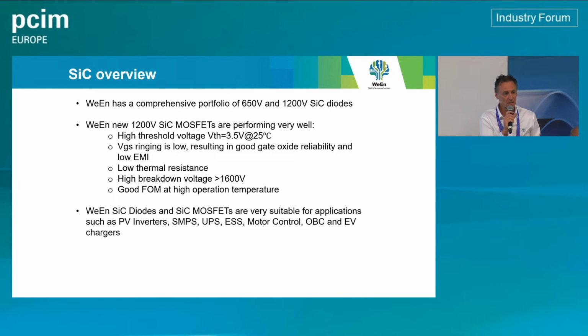So we take away more than half of the material from the wafer to have better thermal performance. Our diodes come in quite a big range of 1 to 40 amps at 650 volts and 2 to 50 amps at 1200 volts. So we also have silicon carbide diodes in the very small packages like SMB. Then we have singles, doubles, etc.